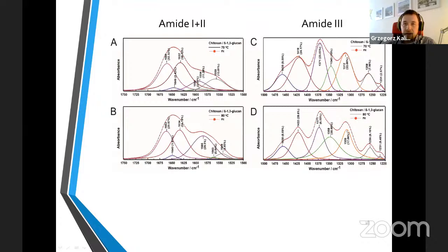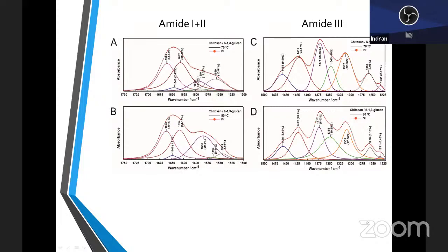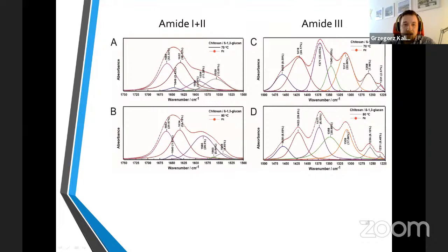To investigate it even further, more information was acquired from second derivative spectra of amides 1, 2, and 3 to monitor changes in intensity and resolving broad overlapping bands into individual bands, resulting in the accuracy increase. So beyond slight shifts, there is band loss at 1577 and appearance of two new ones. Variations in the spectral range mean changes in secondary structure. The alpha helices content decreases and the protonation occurs, which suggests different chain folding, cross-linking at temperature of 80 degrees. So this higher temperature. In this figure, you can see that each band is assigned to maximum and percentage share of entire surface area.